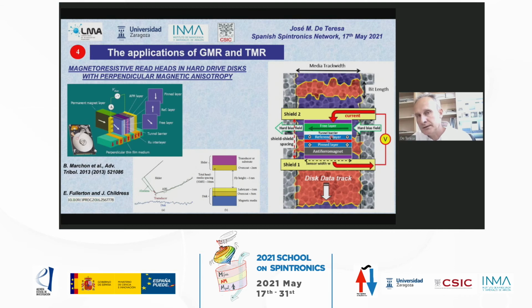This is pinned, the magnetization of this layer is pinned by an antiferromagnet. It's not a simple antiferromagnet, it's a synthetic antiferromagnet that I think will be explained in another talk. I don't have time to explain it now. But you see also the cross anisotropies, which will give rise to this linear response at low field. So we displace this read head on the track, and then we read the information by moving the magnetization direction of the free layer and obtaining a change in the resistance of the head. So this is the technology nowadays.